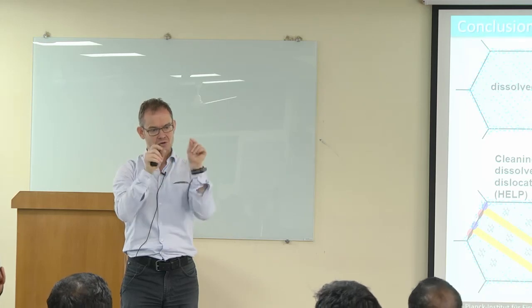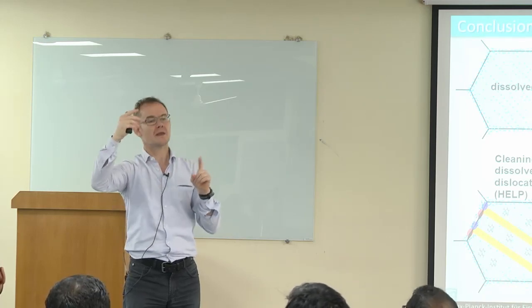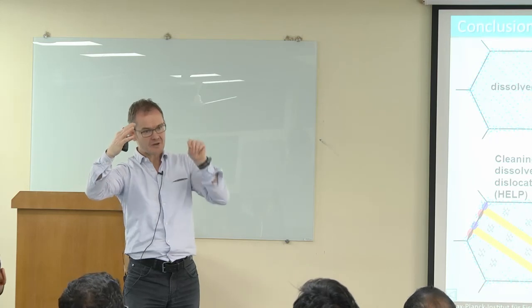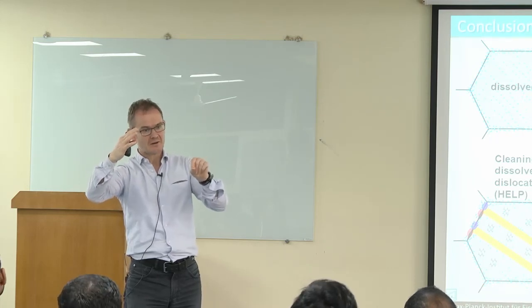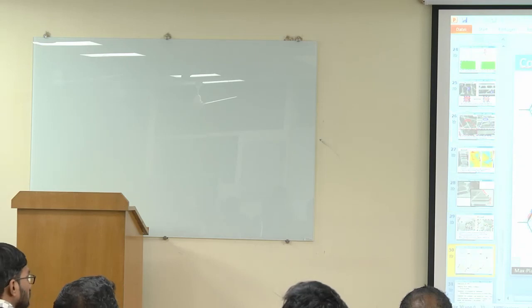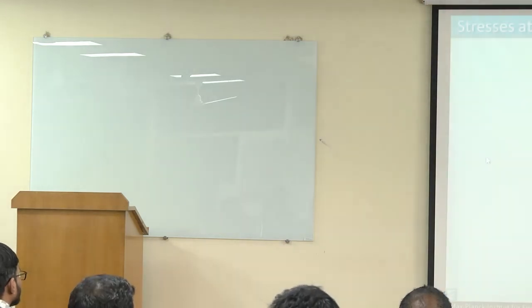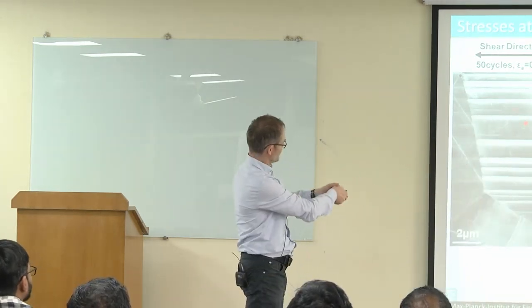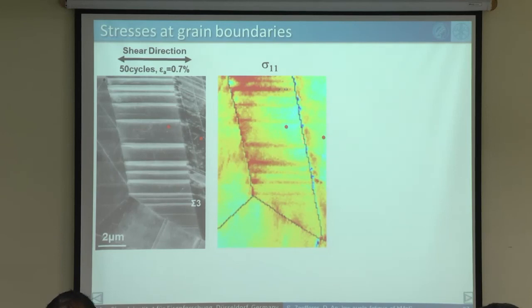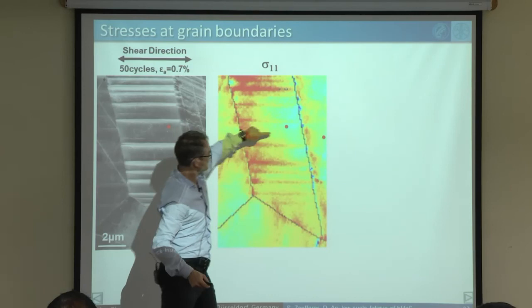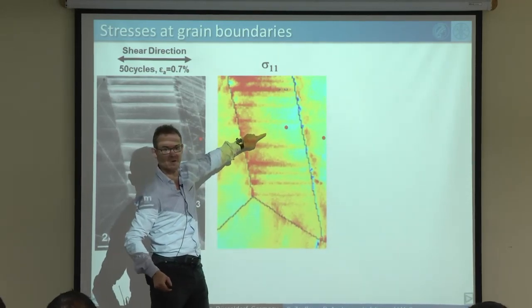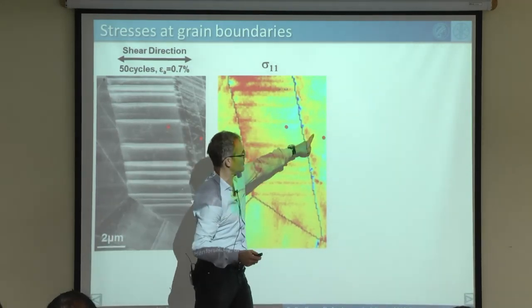So you can only do cross correlation of an area close to the grain boundary with a place inside that same grain. Of course, that's what we did here. Here, this is the epsilon martensite, and we measured the stresses at the grain boundary. But we can only relate a point at the grain boundary with a point inside that same grain. We cannot say what it is across.